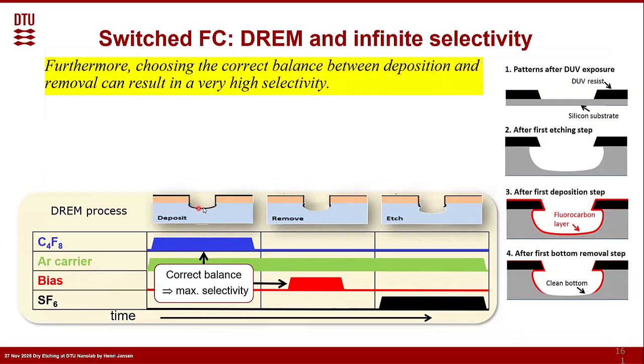So we deposit a layer here, and we tune this time such that it is just gone, and then we etch. So we can really have an extremely high selectivity. And because we deposit everywhere, maybe uniformly the same layer, it can be even infinite. If we put it correctly, we can go to extremely high selectivities. Because the structures get higher and higher, like before, we saw that RIE lag is going to deposit less at high aspect ratios. It's not only etching less, but also the fluorocarbon deposition will be less at the bottom of structures.